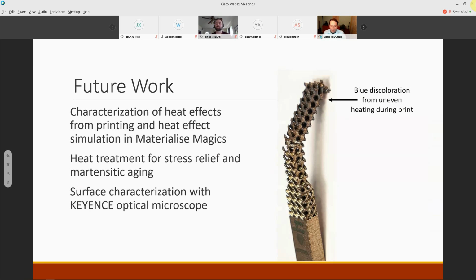We also didn't conduct any heat treating of the parts, so there's still a large amount of internal stress in the parts, which could also contribute to premature bending and cracking. And we didn't conduct the martensitic aging process, so that would actually almost double the strength of our parts. And finally, more thorough surface characterization with Keyence optical microscope, which the school just got. And that would allow us to really make good comparisons of the surface roughness between the polished and unpolished parts.